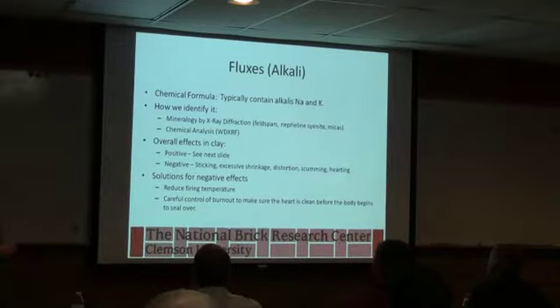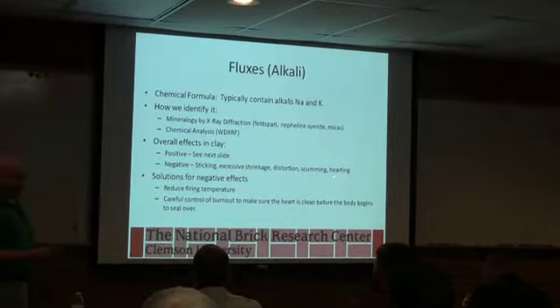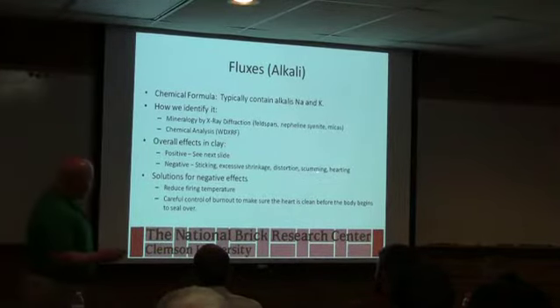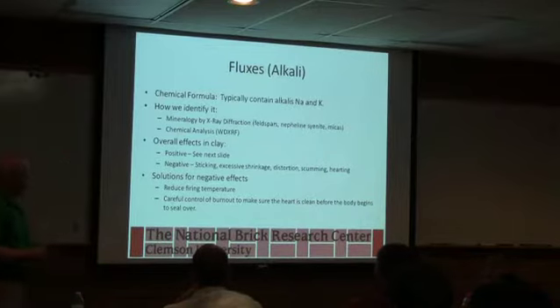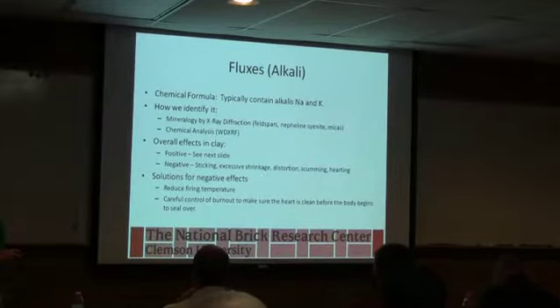We've talked about fluxes. If you go too crazy on fluxes, you can get sticking, where the brick don't want to come apart. Excessive shrinkage, distortion, depending on what form that sodium is, because sometimes we'll try to add a salt to help get better water absorption, and because it's usually soluble, that can result in scumming. We'll skip over some of that, but that's some of the other stuff we look for.